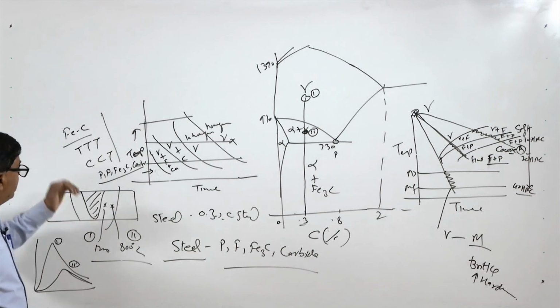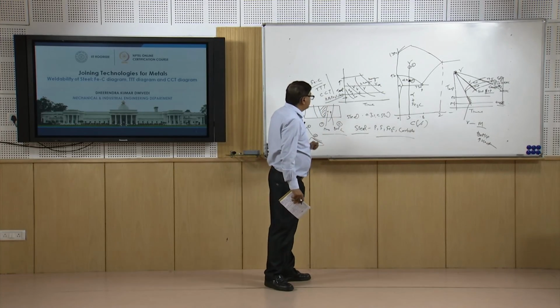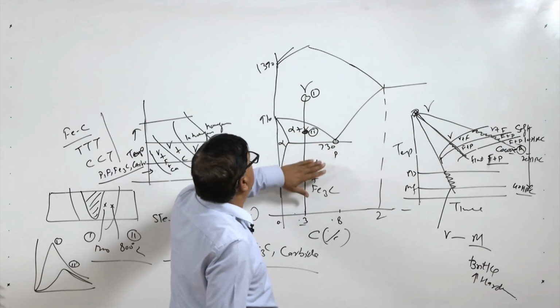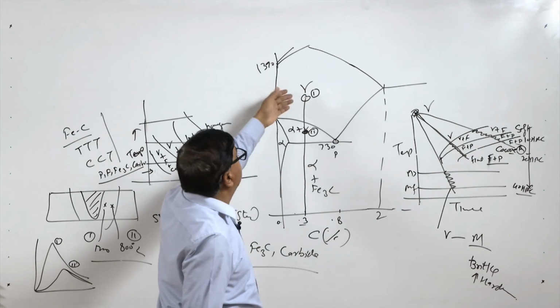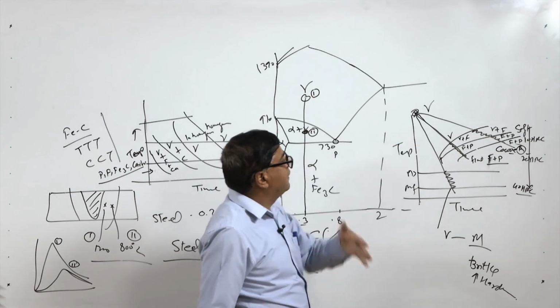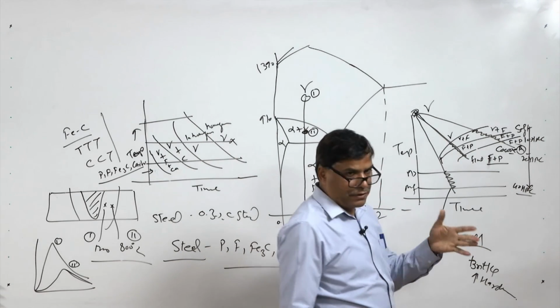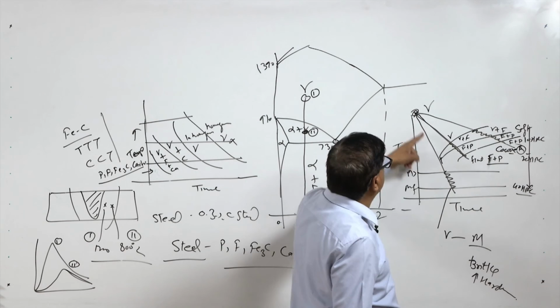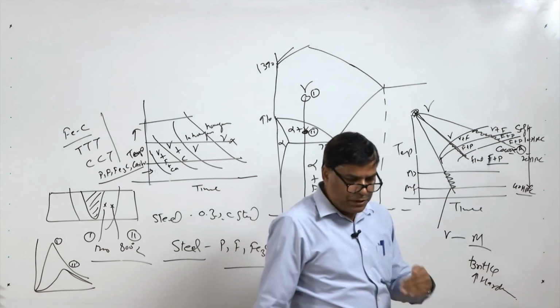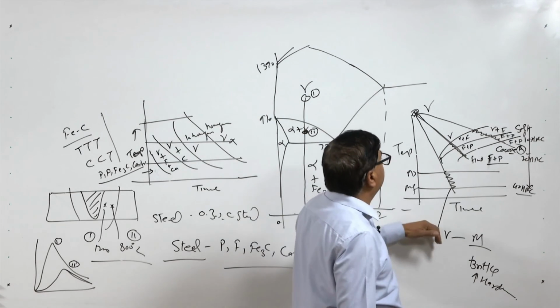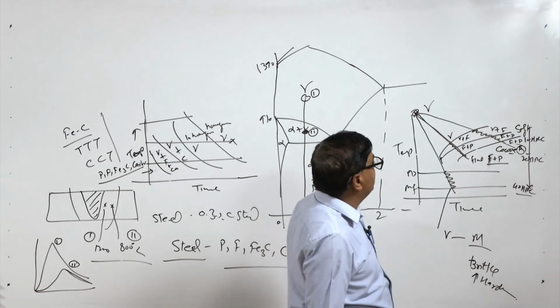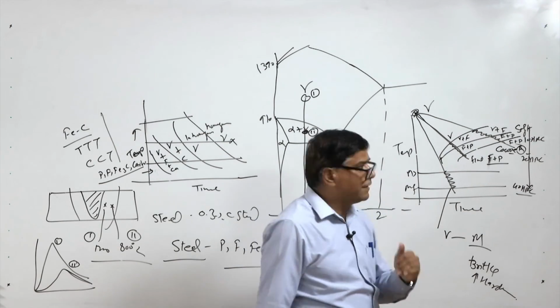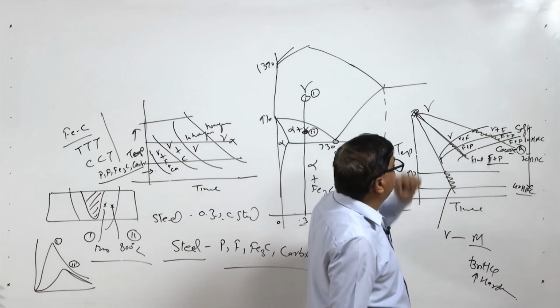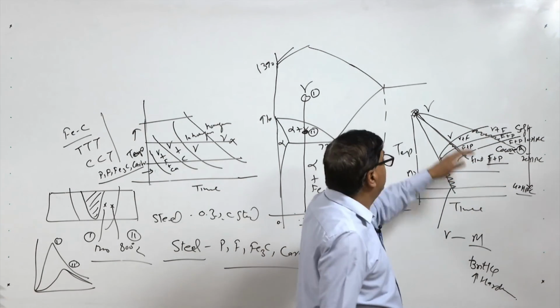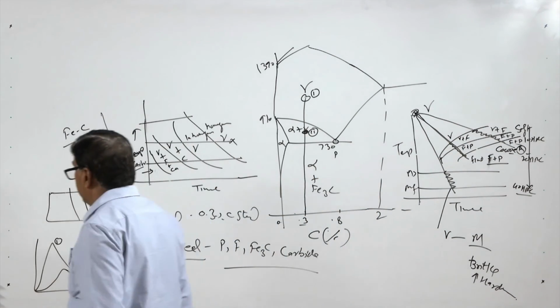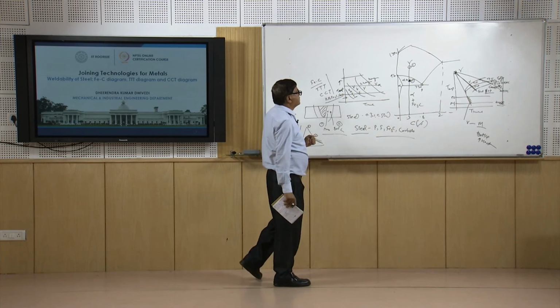the weld thermal cycle being experienced by the heat affected zone, and the iron carbon diagram, how the austenitic transformation takes place, and then when two different points cool at different rates, what we get at room temperature subsequently on cooling. So, the high cooling rate results in martensitic transformation, which makes the heat affected zone very brittle and of low toughness, while point 2, which is away from the fusion boundary, experiencing the lower cooling rate and lower peak temperature, will have either fine ferrite and pearlite, or coarse ferrite and pearlite, and accordingly it will have its effect on the properties of the heat affected zone.